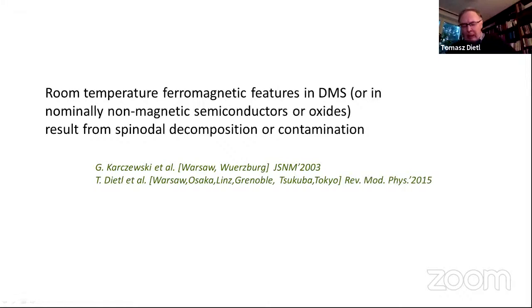So this leads us to conclude, and this conclusion we first got many years ago and we continue to speak about, that if you observe a room temperature ferromagnetic feature in a DMS or in nominally non-magnetic semiconductors or oxides, this results from spinodal decomposition or contamination. So we are very strongly pushing the idea that all these ferromagnetic features at room temperature come from aggregation of cobalt, or formation of cobalt oxide or cobalt metal precipitates, or also, for instance, gallium nitride with manganese, where manganese nitride aggregates with high concentration. Because you have a high concentration of magnetic impurities in a diluted system, it is very probable that you have room temperature ferromagnetism.